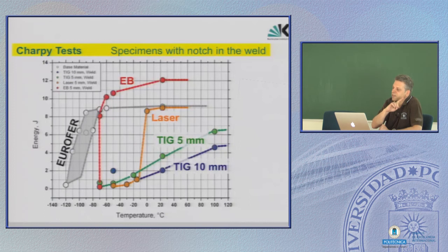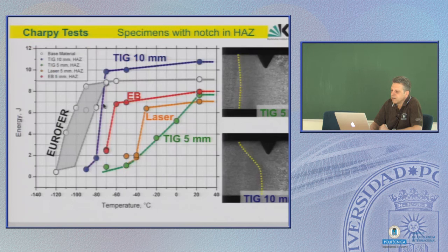Again, this was with the notch directly in the center of the weld, and now the same test with the notch at the heat affected zone. Then all of a sudden the tungsten inert gas welded Eurofer specimens don't look so bad, but still tungsten inert gas with 5 mm thin plates doesn't look good. I don't know whether this is a question of where exactly the notch is located. The dependence on that could be in the vicinity of a few parts of a millimeter. Could also be a very specific thing of these TIG plates and filler material.